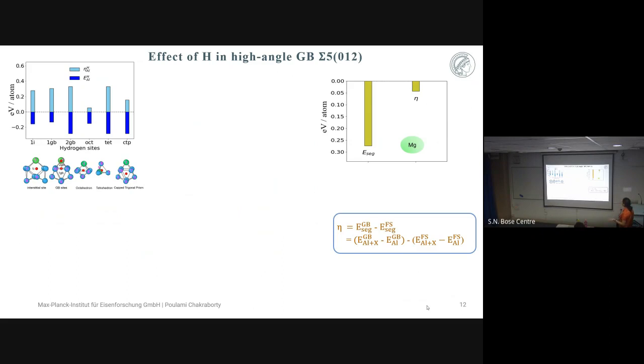and this implies that magnesium stabilizes the aluminium. If there is pure aluminium and a sample with magnesium, the presence of magnesium in the aluminium stabilizes the aluminium further. But this eta, which is the embrittlement factor or the strengthening mechanism, is very, very low. It's close to minus 0.02, which says that it has almost no effect. That is, if magnesium is present, it wouldn't care whether it is at the grain boundary or at the free surface.